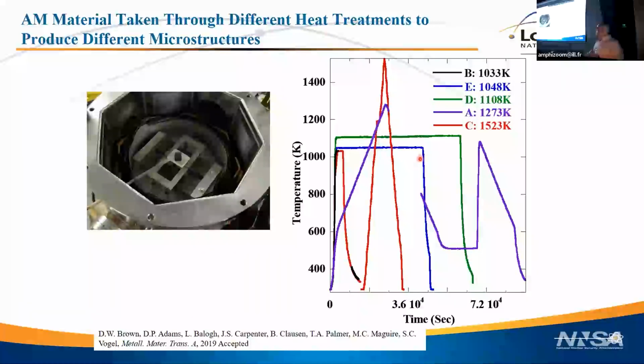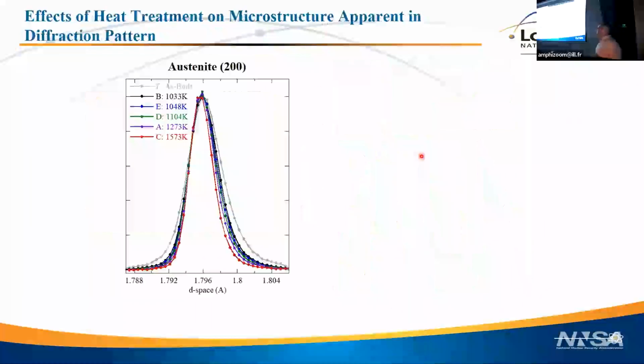And we monitored the microstructure while this was happening, so we could see what parts of that additively manufactured microstructure came out during that heat treatment. And then we tested it again to see how that affected the strength. So for instance, you can see as a function of heat treatment temperature, how the peak breadth decreases. So the gray is as built, you see it's a very broad peak, and the higher the heat treatment temperature, you see the peak gets narrower. That's a pretty clear signature.